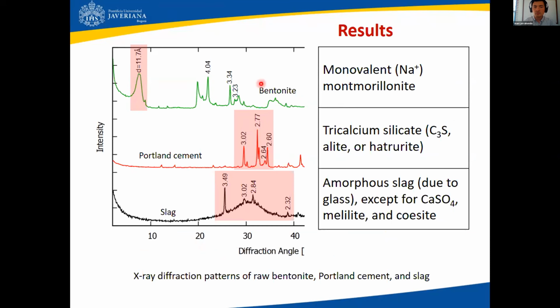So for the bentonite, we confirmed, of course, that it was a monovalent sodium montmorillonite, and that has to do with this main peak that you can get from random powder X-ray diffraction testing. It's in the order of 12 angstrom or so, the D spacing I'm talking about. And that gives us positive identification of the bentonite.